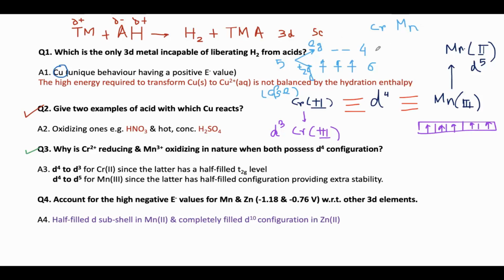But in the case of chromium, because it has lower charge density, it will release the electron and go to the stable d3 configuration. But the same will not be applicable for manganese. Manganese 3 will take up the electron to make this d5 half-filled stable configuration. So that is the reason why, despite having the same electronic configuration, that is d4, chromium 2 is a reducing agent, but manganese 3 is a very strong oxidizing agent.